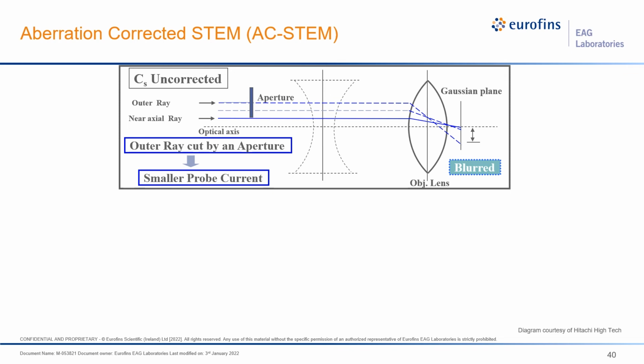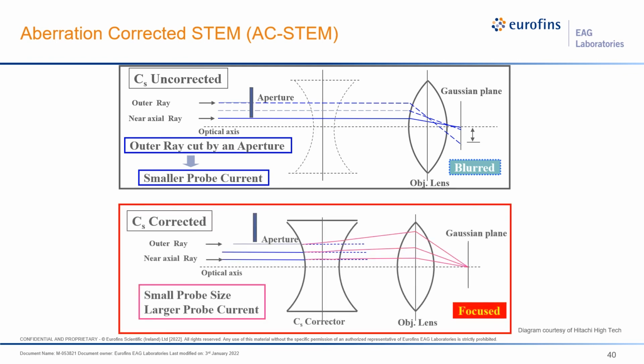But ultimately what we do in the case of aberration corrected STEM is we add a corrector which adds in the negative spherical aberration coefficients of the objective lens, allowing us to focus even the off-axis electrons to a very fine spot. So the ultimate takeaway is we get a smaller probe with larger probe current. So this really enables another level of discretion as far as spatial resolution and signal to noise for analytical work, both imaging and for things like EDS and EELS, which I'm not really getting into a lot here, but are definitely techniques that are of interest more on the materials characterization side.